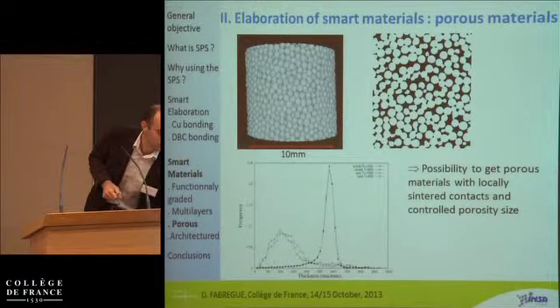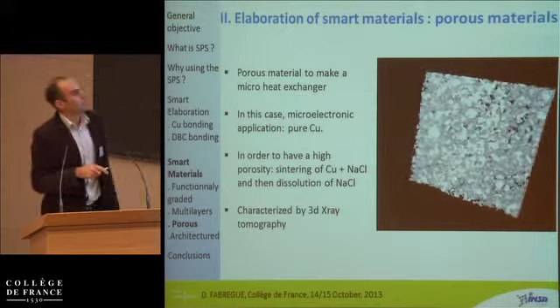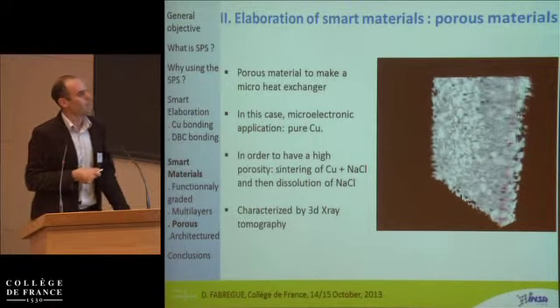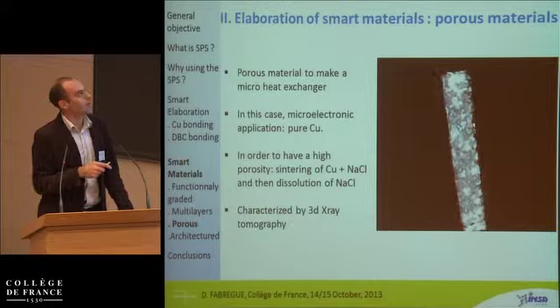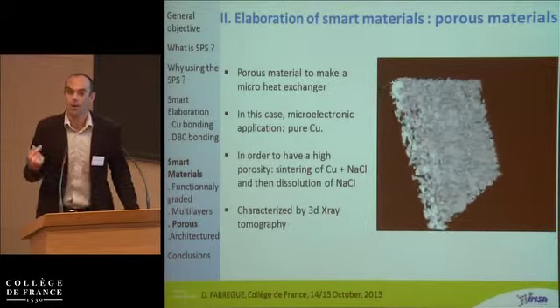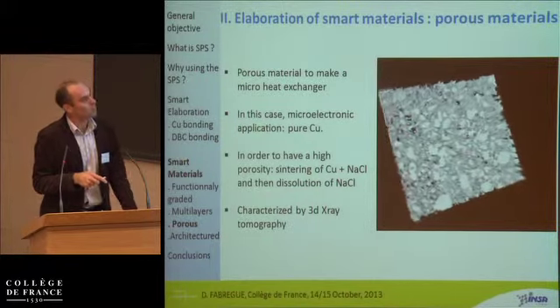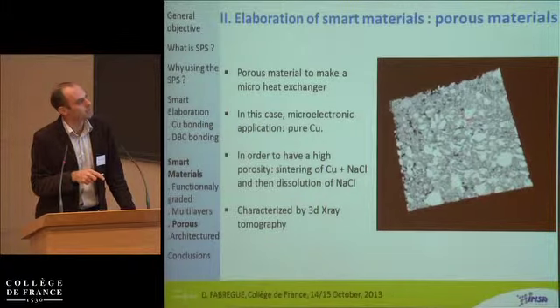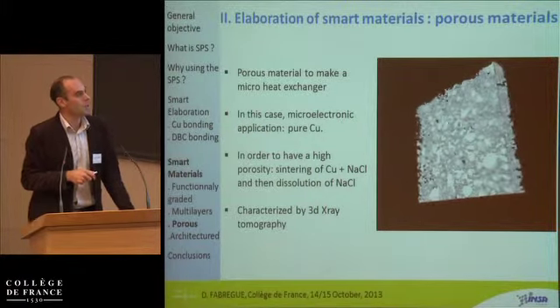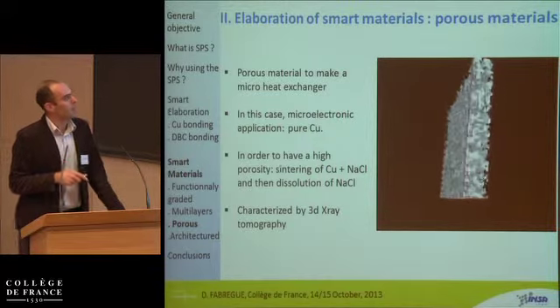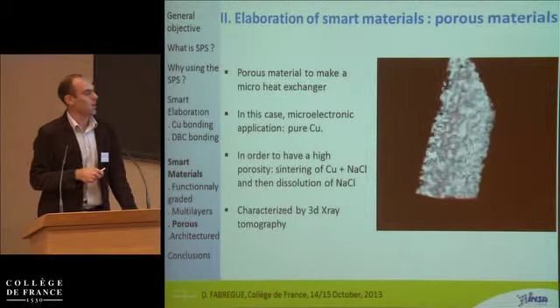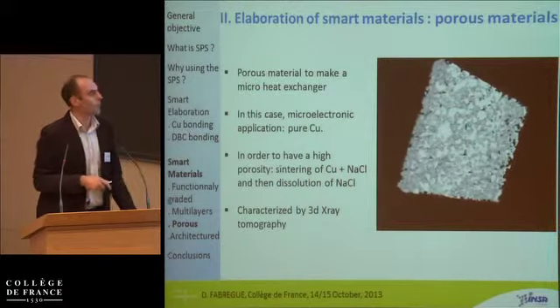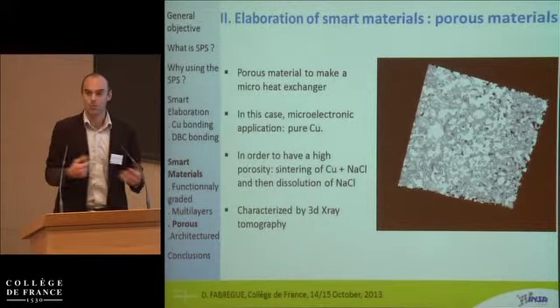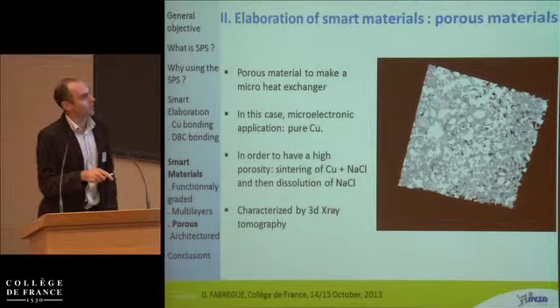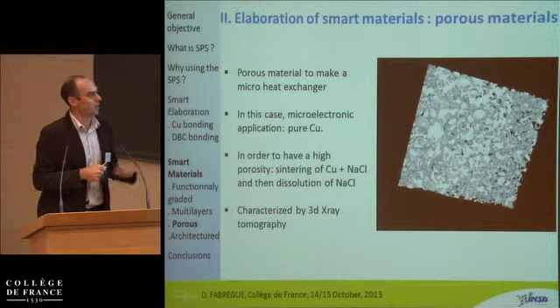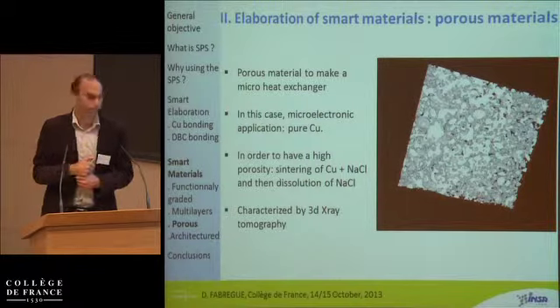Now there's another type of thing you can do. This is another type of experiment we have done, for micro heat exchangers. So we now use copper powder, but you want to have a very high porosity, as you can see here. The porosity is very high, about 60 to 70%. In that case, we mix the copper with sodium chloride. So you sinter the two of them, and then you dissolve the sodium chloride, and you can get this type of structure. And now we are trying to develop that for micro heat exchangers.